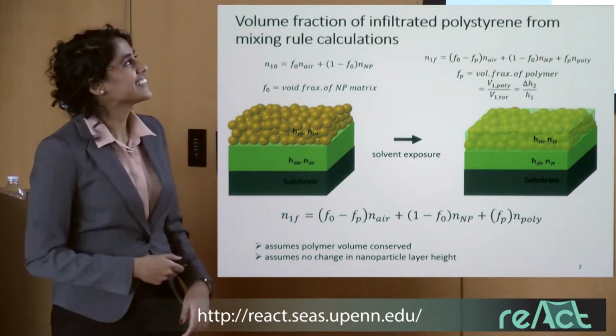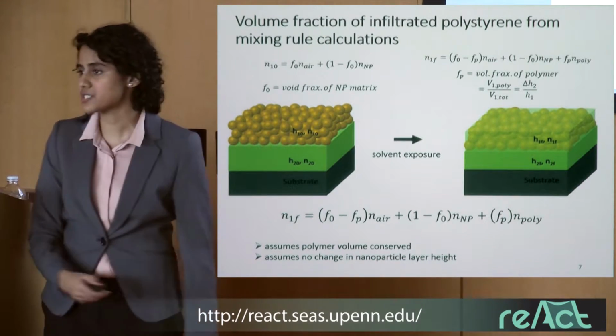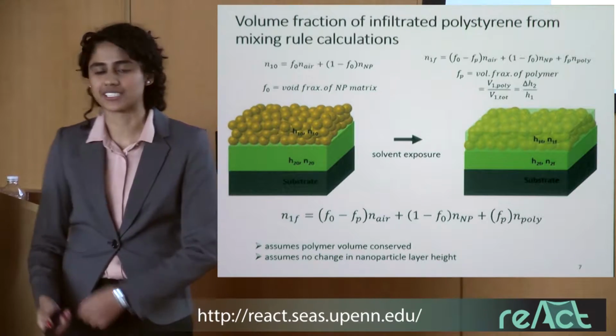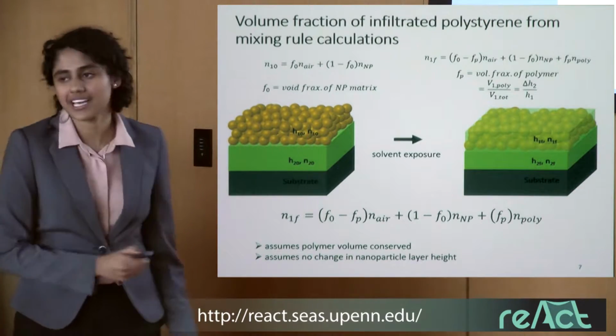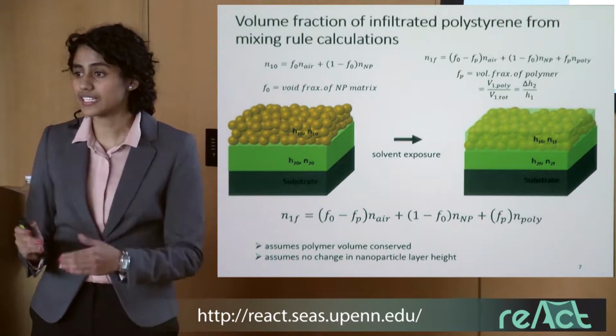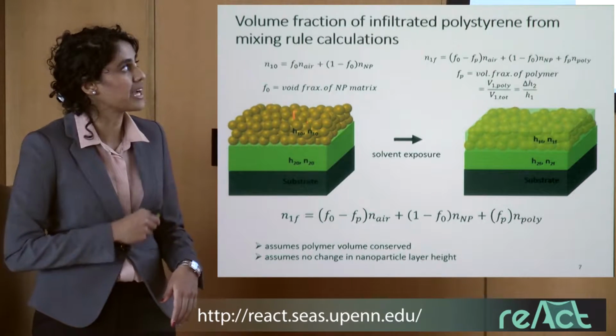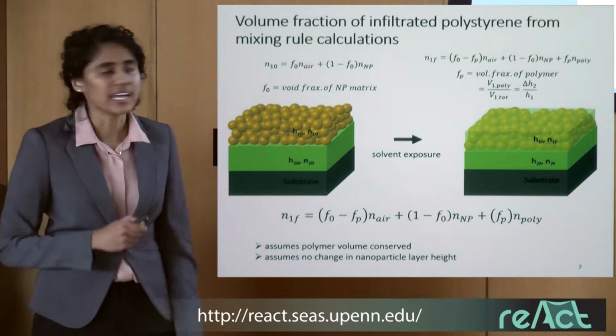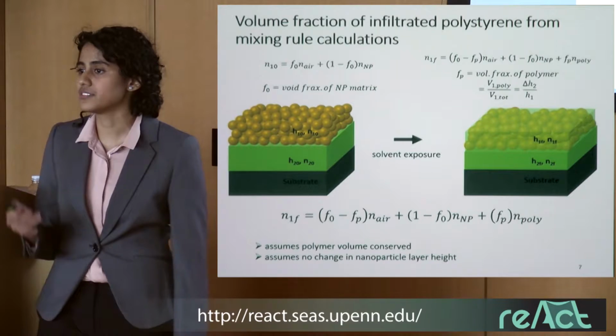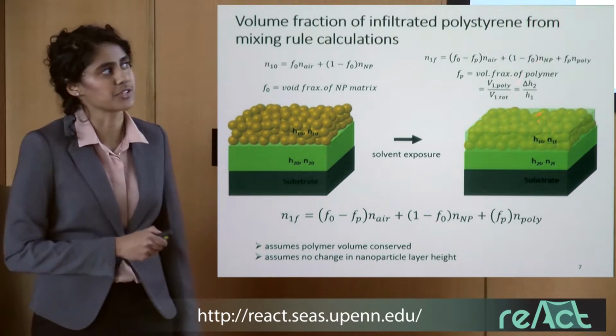But how we study this system is using ellipsometry measurements before and after infiltration. So basically you can get refractive index and thickness values for the bilayer before infiltration, and then you can compare that to the refractive index and thicknesses of the layers after infiltration.